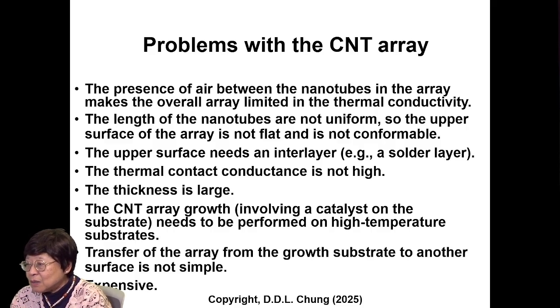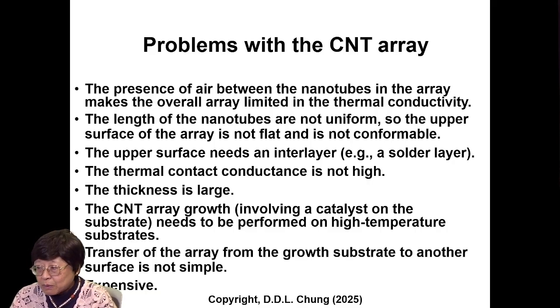So the problems with the CNT arrays are these. The presence of air between the nanotubes in the array makes the overall array limited in thermal conductivity. The length of the nanotubes are not uniform, so the upper surface of the array is not flat and is not conformable. The upper surface needs an interlayer, such as a solder layer. The thermal conductance is not high. The thickness is large. That's good for gap filling. The CNT array growth involves catalyst, needs to be performed at high temperatures and requires high temperature substrates. And the transfer of the array from the growth substrate to another substrate is not simple. Also, the CNT array is very expensive.